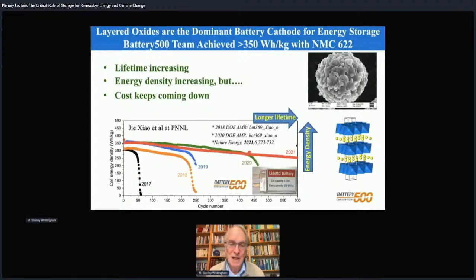And I should emphasize, these are real energy densities. So these are the cells we use. We weigh the cells, we measure the volume, and energy you've got in and out. So be very wary when you see data in literature, it quite often only considers the active materials. So this is where we stand. We expect to go quite a bit further and better.